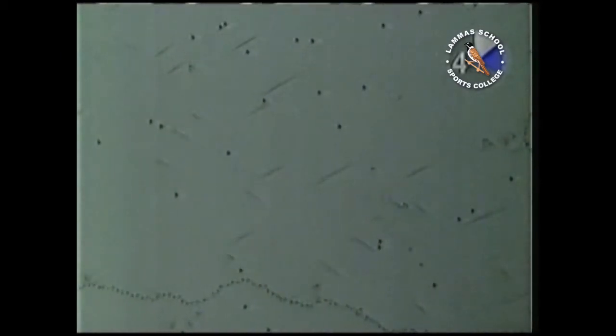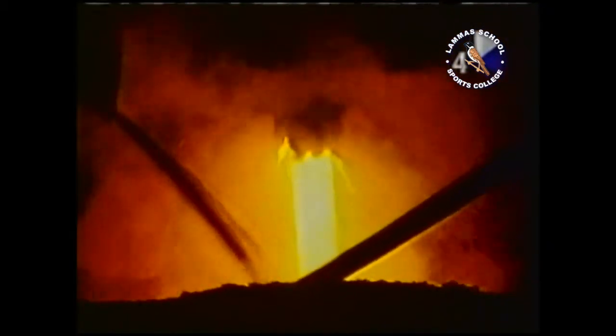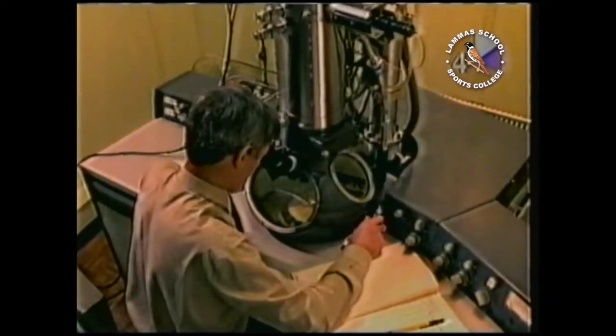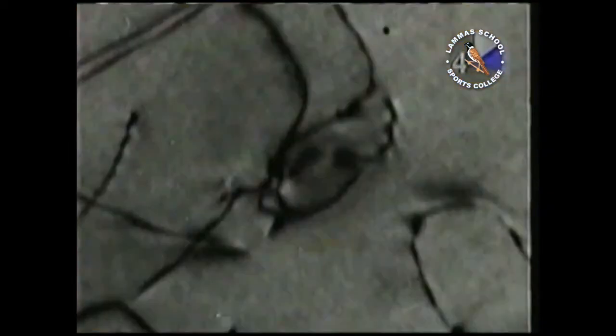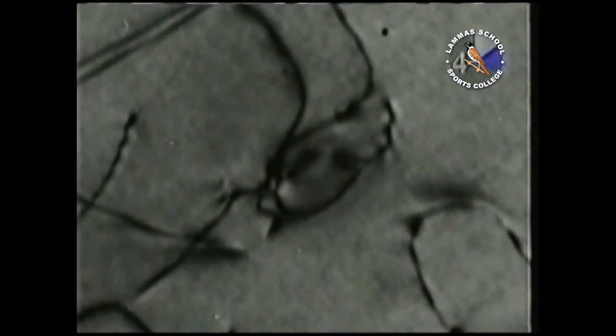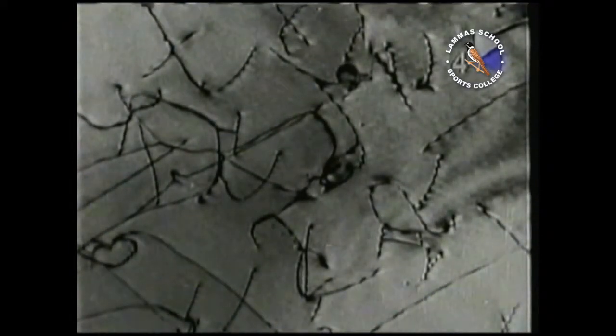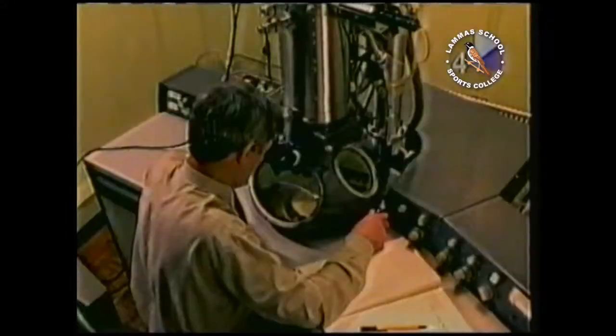The sliding can be controlled by adding elements to the steel, such as niobium. It reacts with carbon to produce fine particles which spread through the steel. You can only see what's going on under an electron microscope — the particles show up as black blobs. The thin black lines, where sliding has taken place, stop at the blobs. The layers of atoms can't slide past each other so easily. Niobium is controlling the ductility and strengthening the steel.